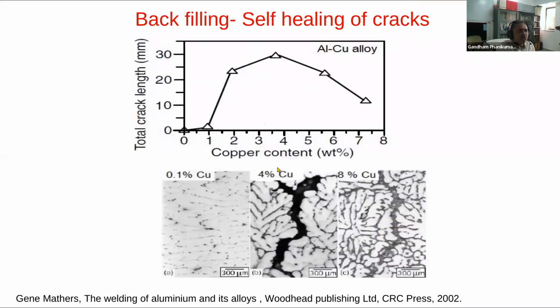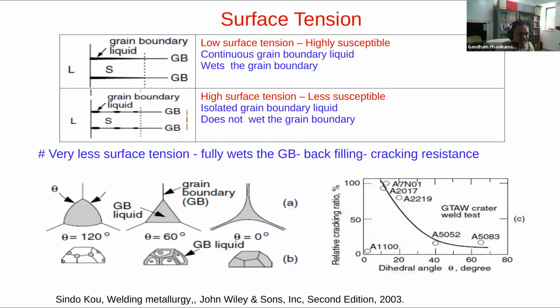Okay. Now, the freezing range also gives a hint about the cracking susceptibility. For any alloy content, you have a freezing range. For example, in the case of aluminum copper alloy, around 4% copper content the freezing range is maximum, and that's also the alloy for which the crack length is maximum. So you can draw a thumb rule: if the freezing range of the alloy is more, that is, if the difference between the solidus and liquidus temperatures is more, then the crack susceptibility is more. Just a straightforward thumb rule we can draw. And how does the surface tension affect? That can be understood as the way by which the liquid can wet and go on to fill the gaps, and that also helps determine which alloys have less susceptibility to cracks.